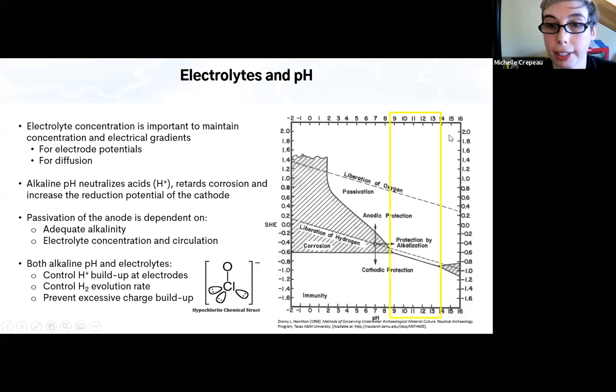Yes, so this right here is the sweet spot of our pH range. Usually 8.5 is the lowest that you want to go in terms of pH. We often use things like sodium hydroxide and sodium carbonate, things that are well on their way in this 9 to 14 reference, to try to control that pH.